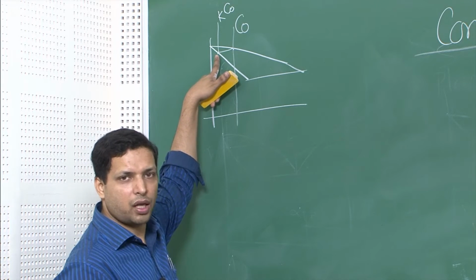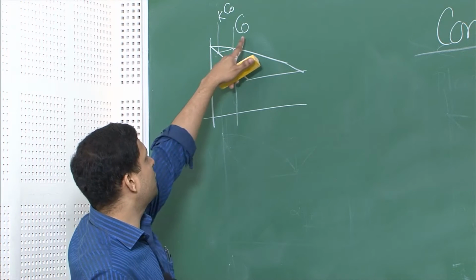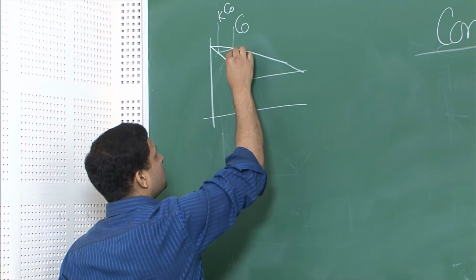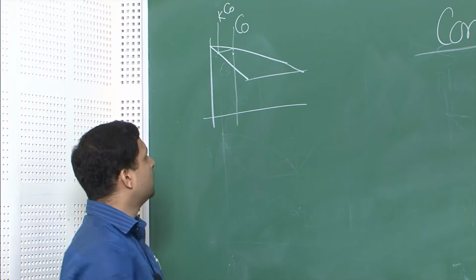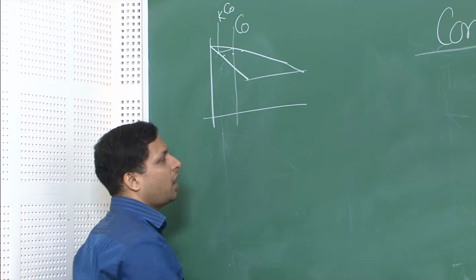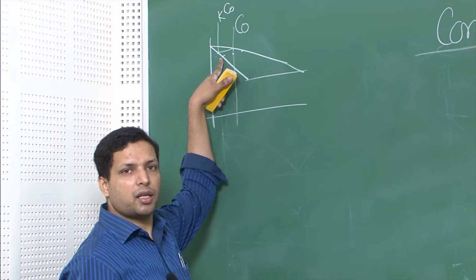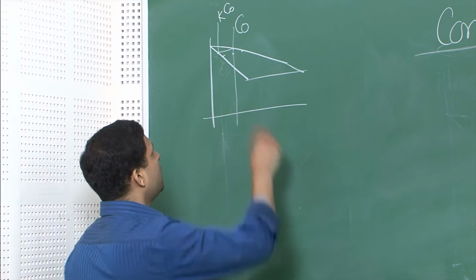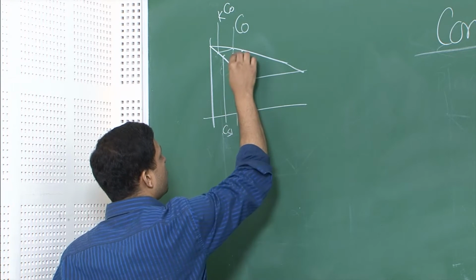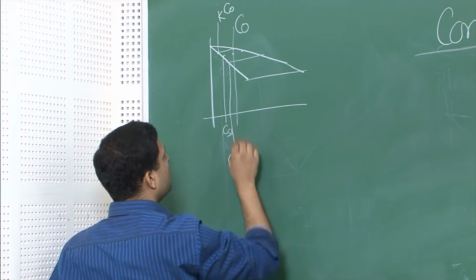Cs by Cl is equal to K. So, the solid composition is equal to K C naught, where C naught is the liquid composition. Now, as you lower the temperature, at this particular point the liquid will have a composition like this and the solid will have a composition like this. So, the solid that forms at that temperature will have a composition like this, Cs1, somewhere over here it will have Cs2, and so on.